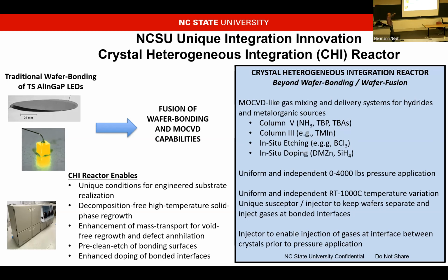To do decomposition-free bonding. I talked a little bit before and showed some of the limitations: if we get the crystal too hot, we see some of the defects that are formed. By having a column 5 overpressure in the tool, we greatly enhance the process window that we can explore to integrate materials. Because we can etch or dope, we can also engineer the interfaces before we integrate the devices.